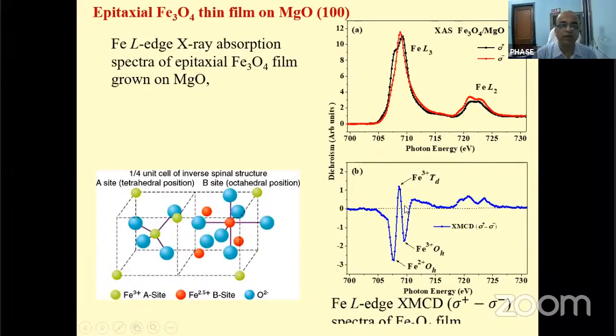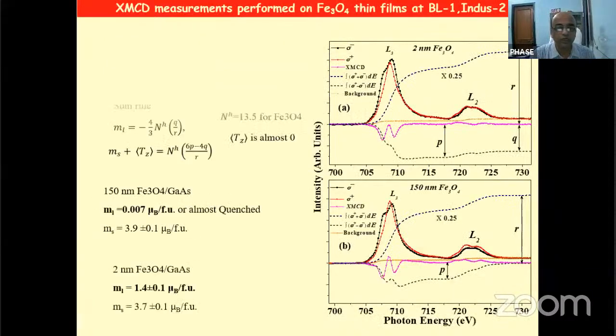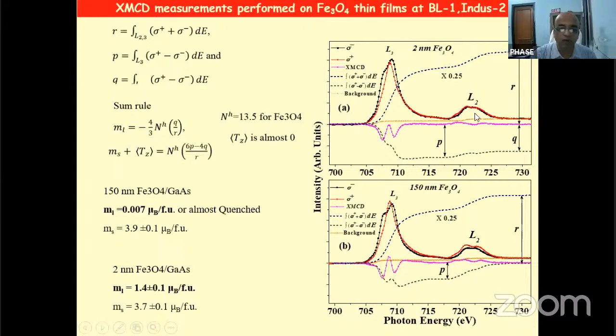Finally, we have concluded that there are 2 types of moment: one is the orbital moment and one is the spin moment. So the magnetic moment consists of L plus S, the orbital moment and the spin moment. We have checked both samples, the 2 nanometer Fe3O4 XMCD measurement and the 150 nanometer XMCD measurement, and we have done the calculation from the experimental data. Finally, we found that the 150 nanometer Fe3O4 has zero orbital moment.